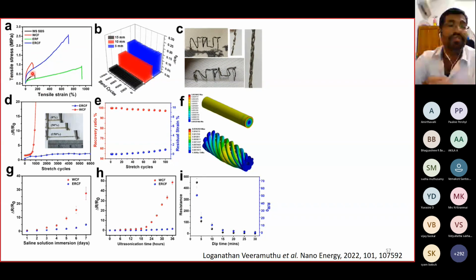And here you can see the differences between the WCF and the ERCF structure. ERCF structures are quite robust. You can see their mechanical strength is enhanced compared to WCF structures. WCF structures are limited within 200 percent strain, but the reinforced structure has very good stretchability, which is confirmed with the simulation studies. We compared the normal structures and the reinforced structures, and we studied the recovery ratio, residual strain, all these things. And we also studied the environmental stability.